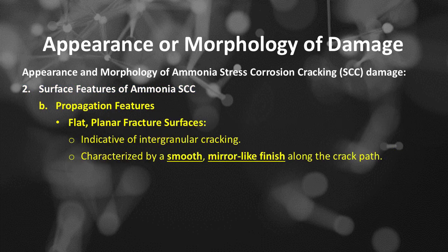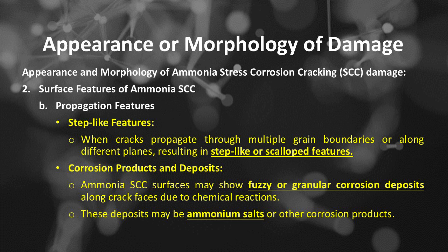Surface features of ammonia SCC. Number B is propagation features, includes flat, planar fracture surfaces, indicative of intergranular cracking, characterized by a smooth, mirror-like finish along the crack path. For step-like features, when cracks propagate through multiple grain boundaries or along different planes, resulting in step-like or scallop features, and for corrosion products and deposits, ammonia SCC surfaces may show fuzzy or granular corrosion deposits along crack faces due to chemical reactions. These deposits may be ammonium salts or other corrosion products.